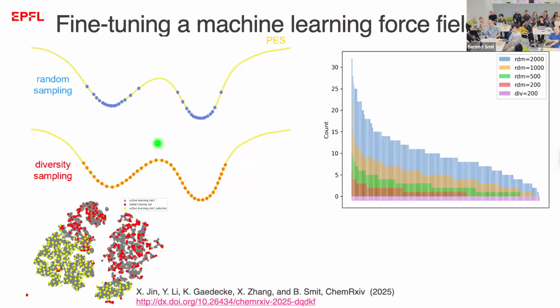You really need to go out of your way to make sure that those rare occasions are actually labeled with DFT, because otherwise, if your barrier is not correct, you may not sample the dynamics that is behind that barrier and those kind of things. And what you then can actually see is the number of samples you need to get a similar diversity is an order of magnitude larger. So yes, you can do it by brute force, but you pay an order of magnitude more.